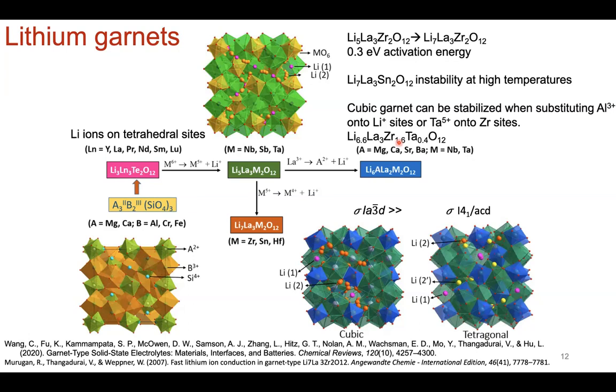Now, when you move to the synthesis of LLZO, however, this is, of course, the crystal structure that people often strive for, the cubic phase as opposed to the tetragonal phase. The cubic phase is the higher ionic conductivity phase. The low temperature tetragonal phase has the lower ionic conductivity. And that has everything to do with where the lithium ions sit.